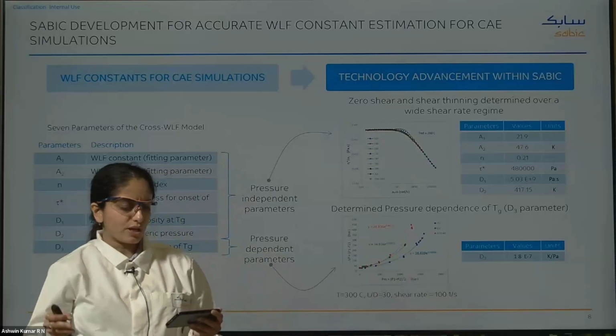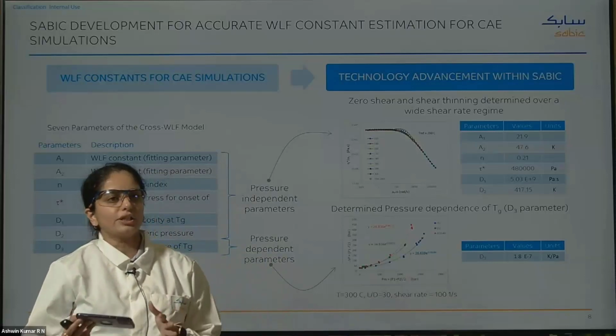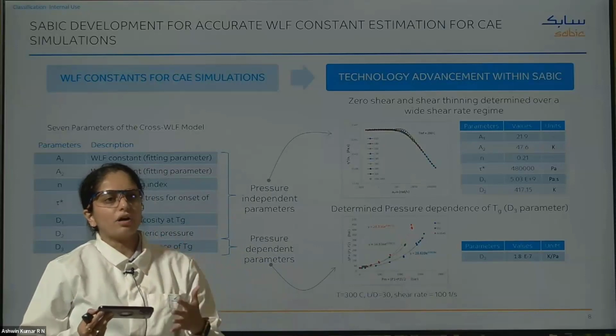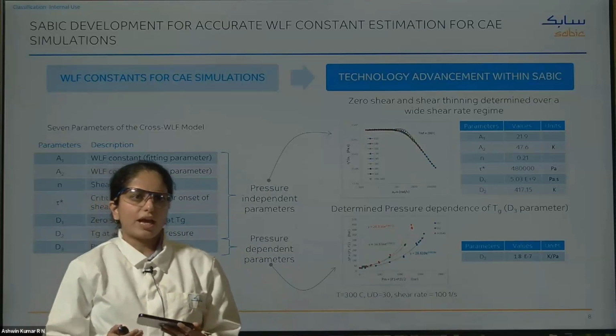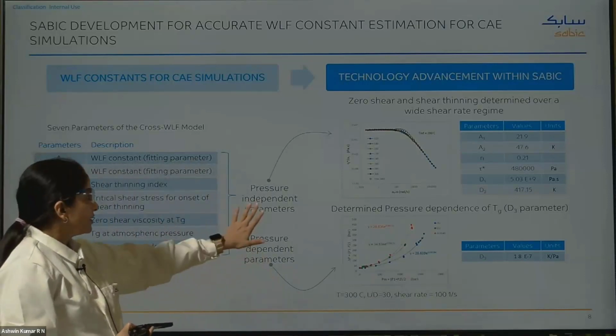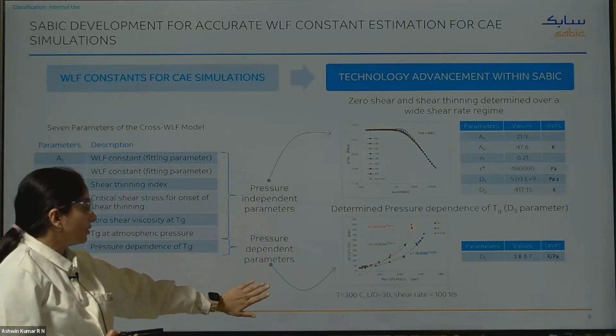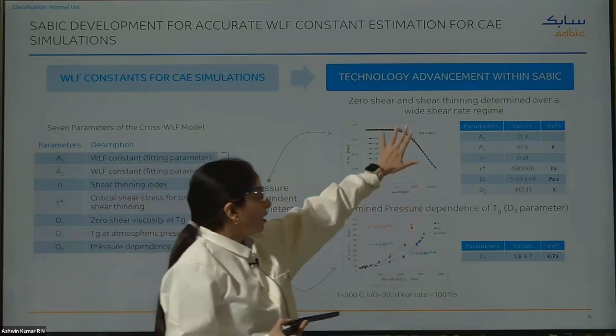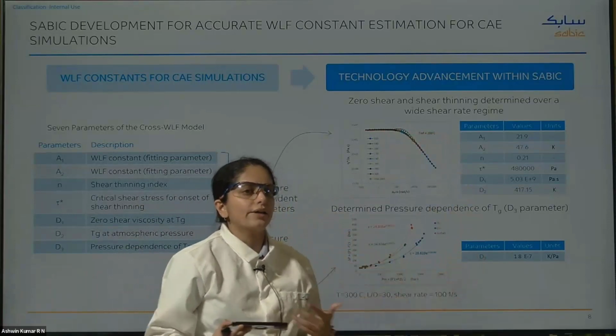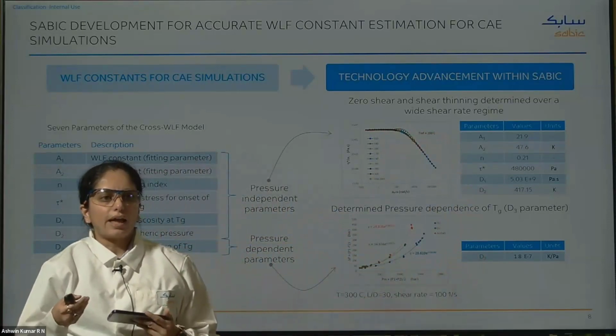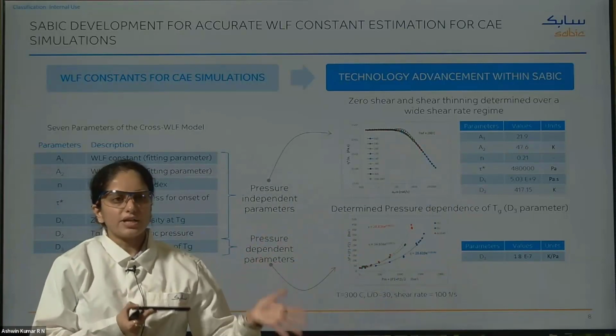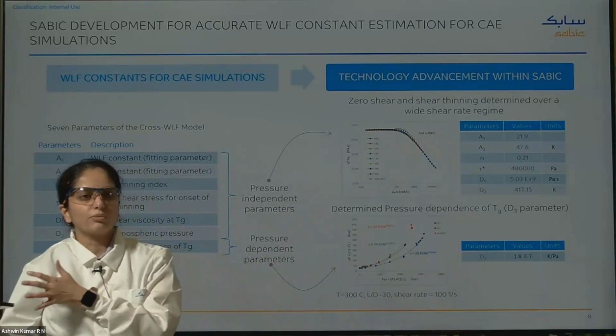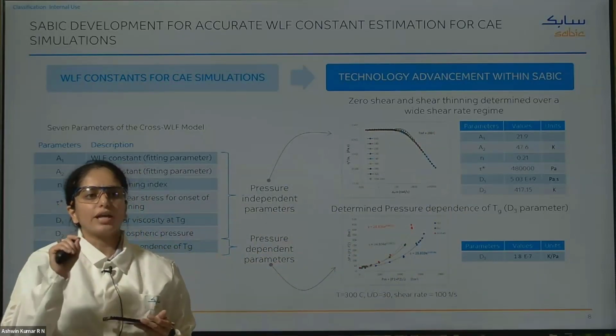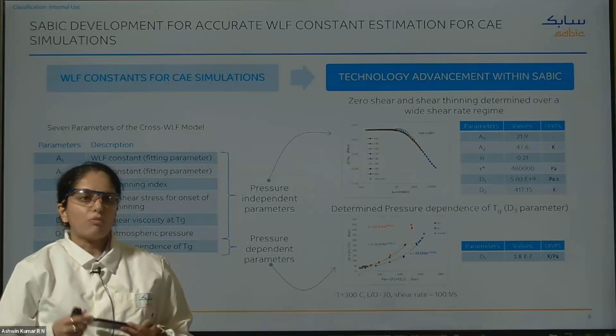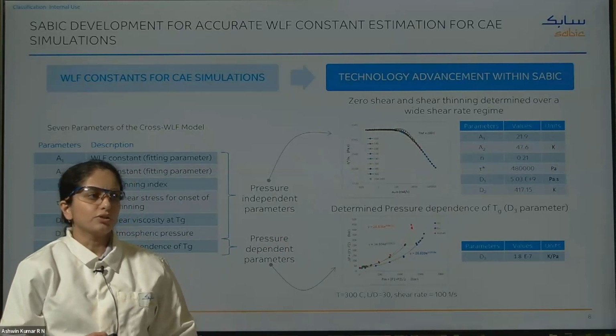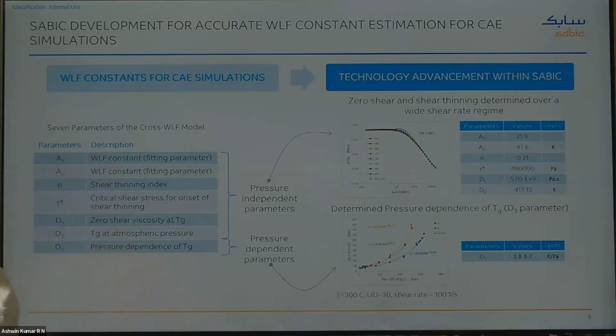So I would like to summarize here that the effects of pressure and shear rate can be decoupled, and then we can have our D3 parameter evaluated, which you can see that there are some pressure independent parameters and pressure dependent parameters, and we can arrive at the 7 parameters of the cross WLF model and provide more complete data in order to characterize the CAE predicted injection pressures and the actual injection molding pressures, and we can bridge this gap by about 10%. So this is our finding, and I would like to hand over this stage now to Ashwin to explain the further molding validation studies. Thank you.